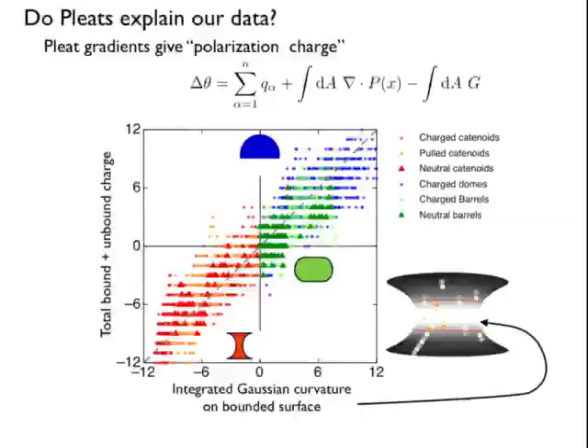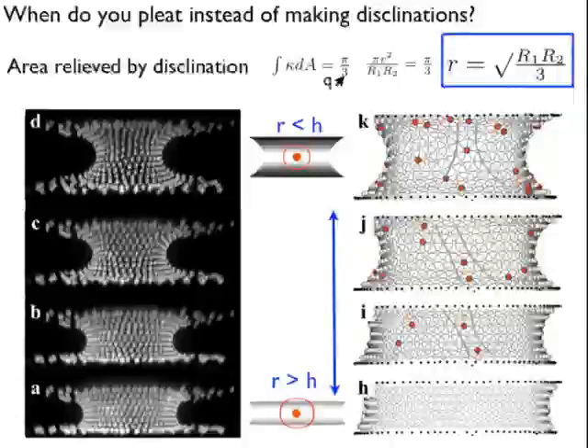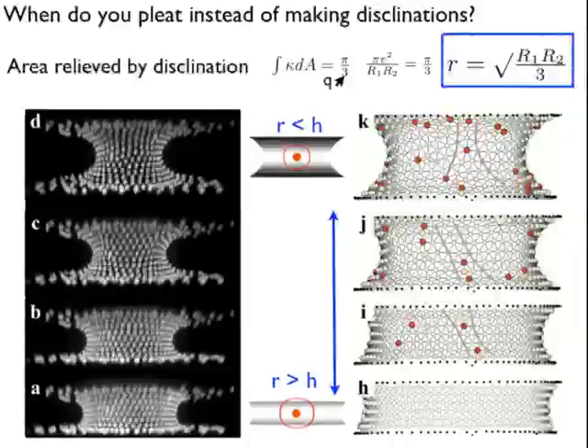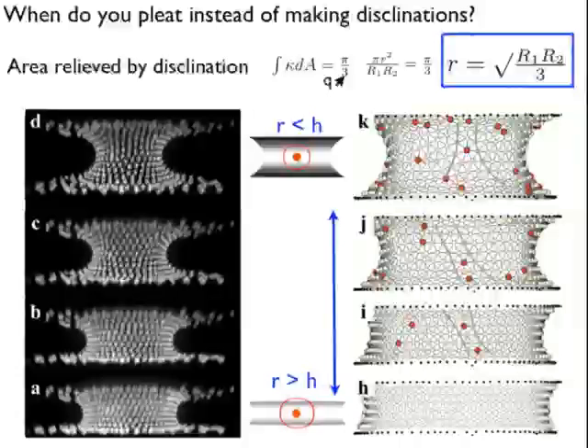Once you know this, and you put in the derivatives of the polarization charge, now you find that instead of having this diodic, rectification type behavior, you in fact get a line here. It's actually kind of cool. If you look at the integrated Gaussian curvature from a disclination, it's pi over 3, and you can figure out from looking at the curvature of the object how much area that should be.